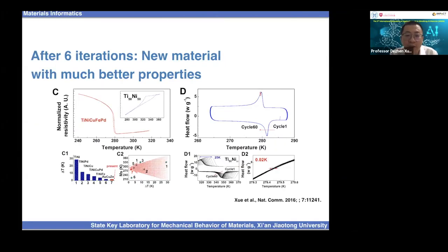So this is our new design alloys, and compared to the commercial one, the thermal hysteresis is greatly reduced, and we have a better thermal stability, and the shift of the transition temperature is very small. It's 0.02 Kelvin.